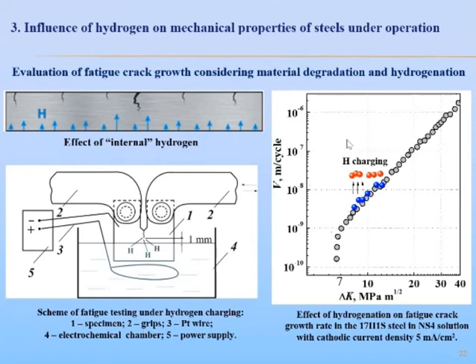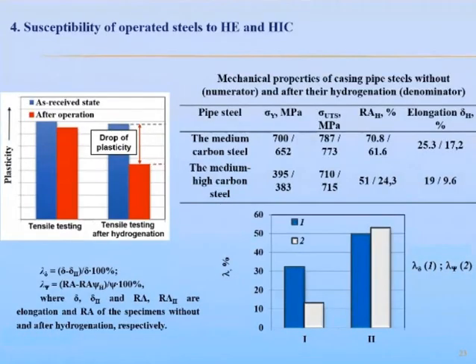And this figure demonstrates such an effect. We can see acceleration of fatigue growth in the operated pipeline steel by internal hydrogen. The next topic is susceptibility of operated steels to hydrogen embrittlement and hydrogen-induced cracking. Generally, operated steels are more sensitive to hydrogen embrittlement. On the right scheme, you can see a little difference between plasticity of different states of steels, but the left one demonstrates a significant difference if we compare results of tension tests of hydrogenated specimens.